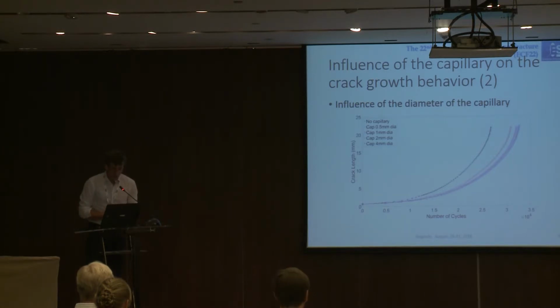So, what are the results from the simulation? It might not be very clear, but let's say the curve most to the right, the blue curve, is the curve for the normal lug, so a lug without capillary. And you see that we come to a crack propagation life of about 32,000 cycles.